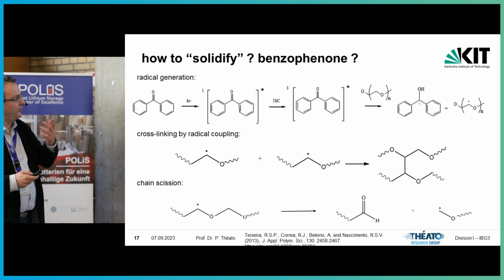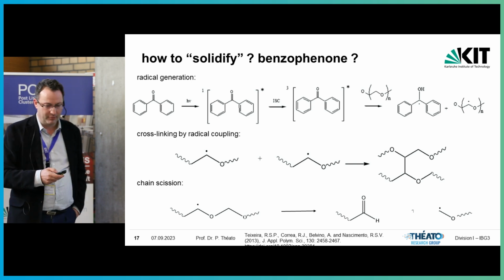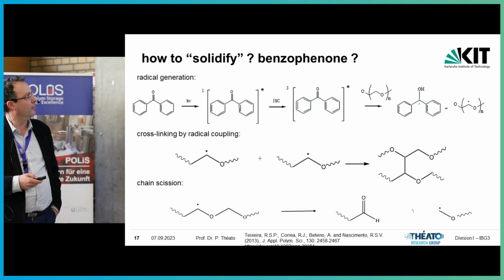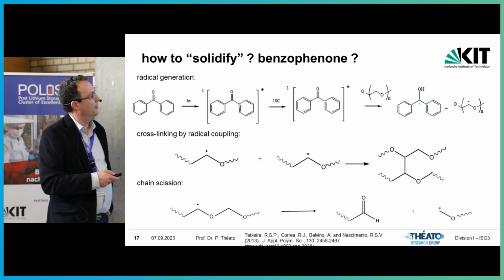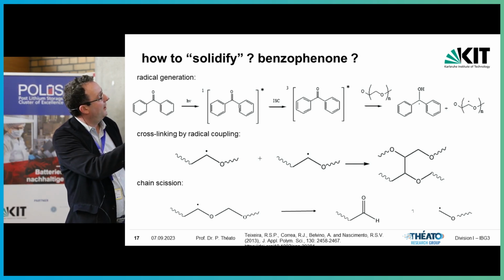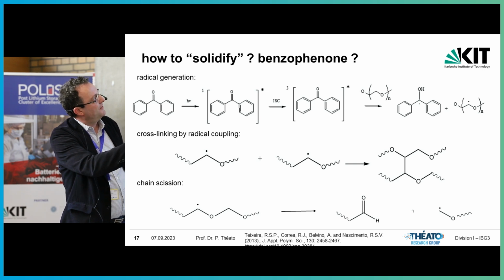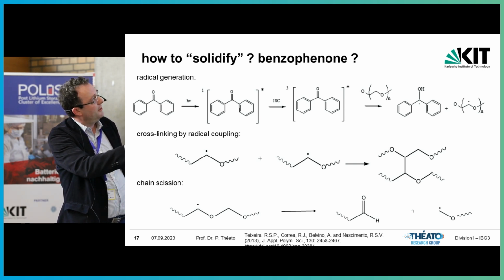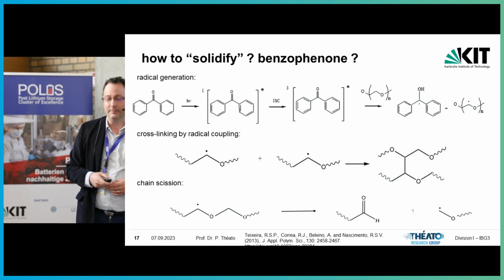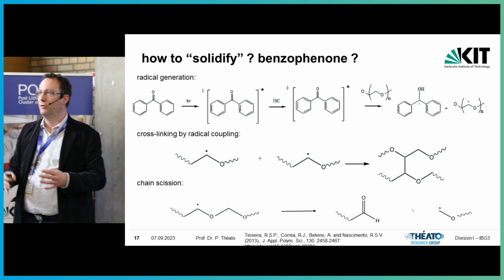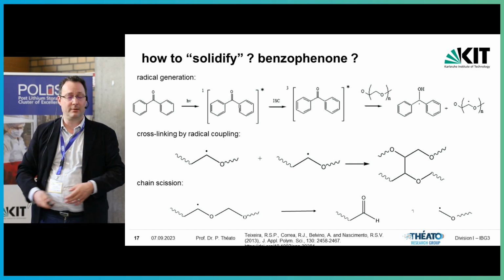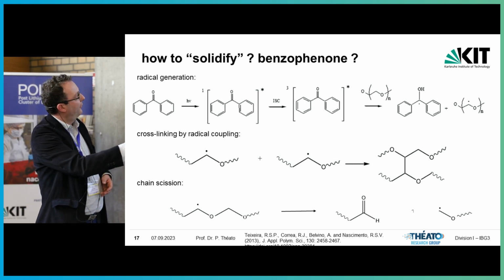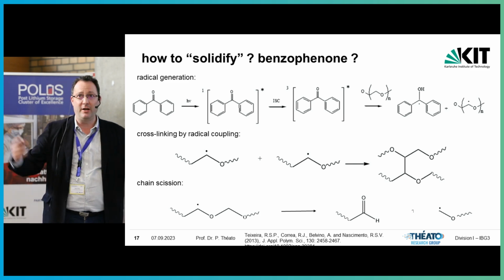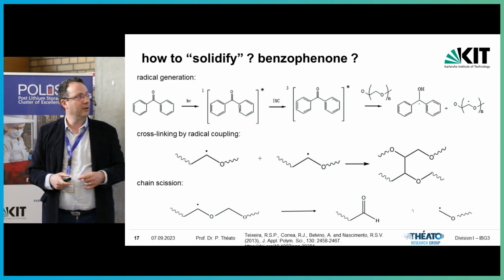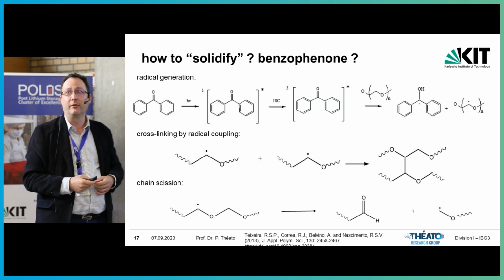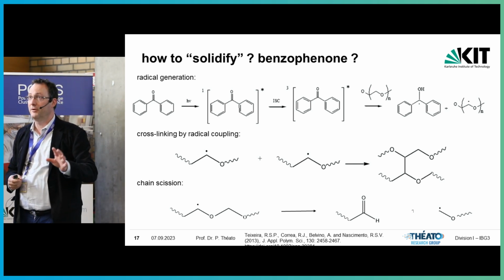You know, I learned something from literature, but I just put this out as a reference to underline my own thinking. If you use benzophenone, this is essentially what's going to happen. You excite the molecule, you have PEO present, you abstract a CH bond in here, you get the radical at the PEO chain in there. And then this radical is supposed to do something that should end up in a cross-linked system. Well, it does so because if two of the neighboring chains by chance have a radical, you get a radical coupling, and that will yield a cross-linked system. This is the reaction you want, I understand.